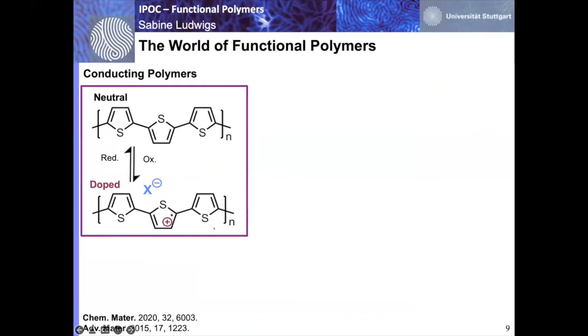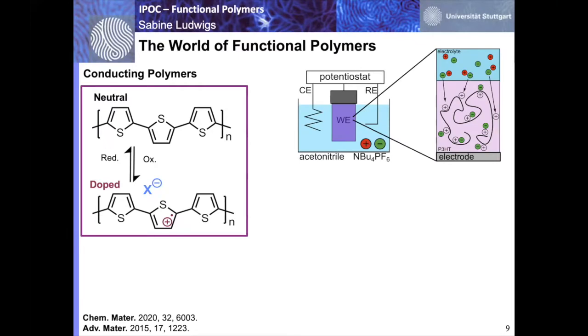And that can be reversibly done, so that you can change between the neutral form and the doped form of this polymer reversibly. You just have to add additional ions to the systems, which then work as counter ions to overall fulfill the rule of counterbalancing charges, of charge neutrality, essentially. This counterbalancing of the charges works, for example, when you do the doping in so-called electrochemical experiments, where you have films of your polymers on so-called working electrodes, and then you put everything into an electrolyte, and then ions can move out of the electrolyte into the polymer.